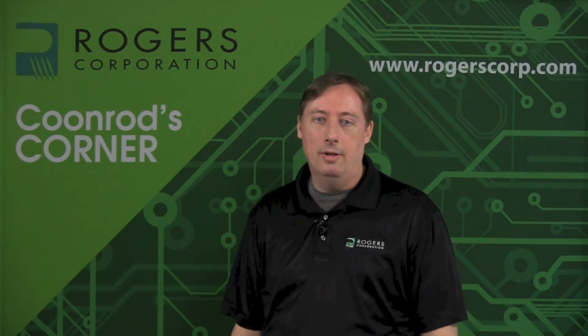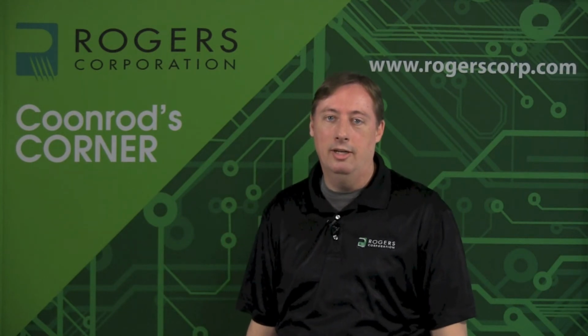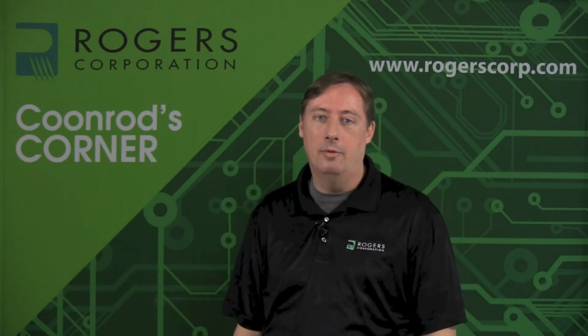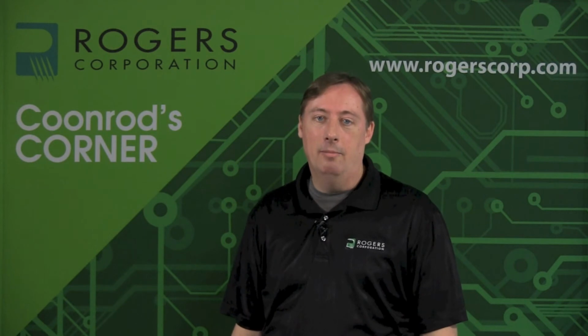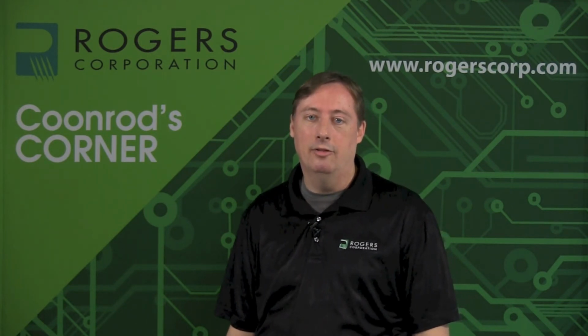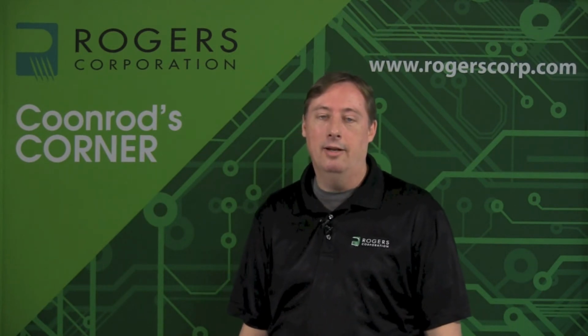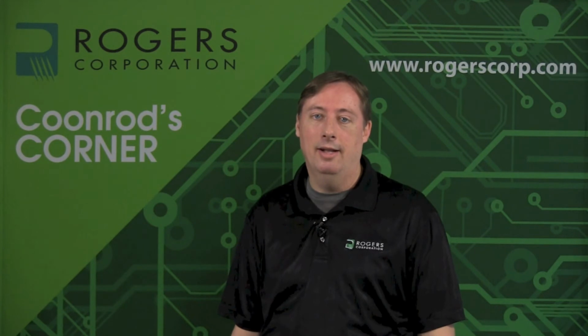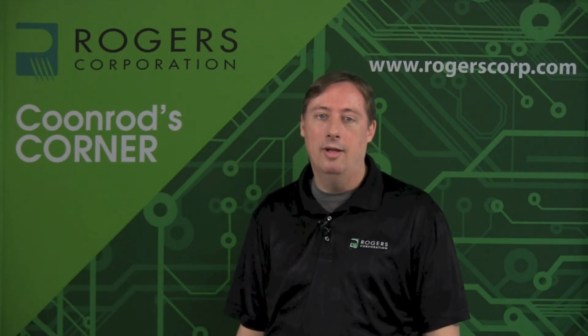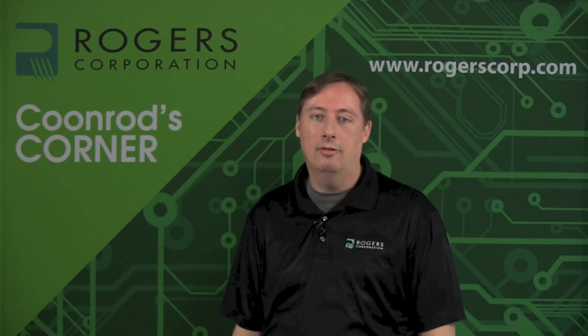Now, one of the more common plating finishes in the printed circuit board industry is ENIG, which stands for Electroless Nickel Immersion Gold. ENIG is a very good plating finish. However, it does have more conductor loss due to the nickel being less conductive. The nickel is about 1/3 the conductivity of copper, and because of that, it makes more conductor loss, and the insertion loss of the circuit increases some.